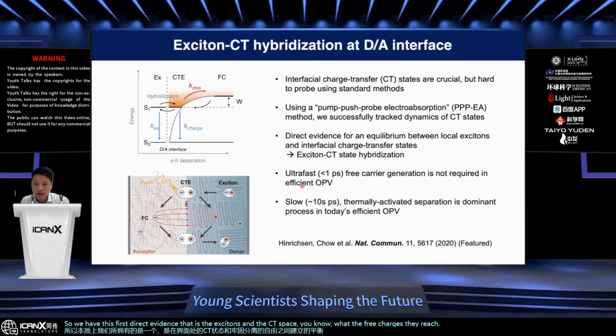Furthermore, if we look at the delayed time-correlated photoluminescence, what we found was that the emission from exciton states can go all the way beyond a nanosecond timescale. So basically, we have all three states in a steady state. Once we form CT states, they can go one way, but they are also hybridized with the exciton state, such that energy can be exchanged back to the emissive exciton state as well. This is what we found, and it was published a few years ago.